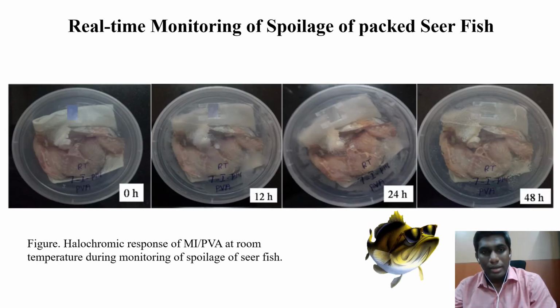And then we also subjected the halochromic thin film for real-time monitoring of the spoilage of the packed seer fish. In Tamil, it is called vanjanam meen. It's one of the commercially important fish, and people prefer it because of its richness and bonelessness. At 0 hours, I mean the starting of the experiment, we observed the blue color of the sensor. On the time scale, the color fades and changes into the gray region, and at 24 hours, we can see that it's completely gray in color.